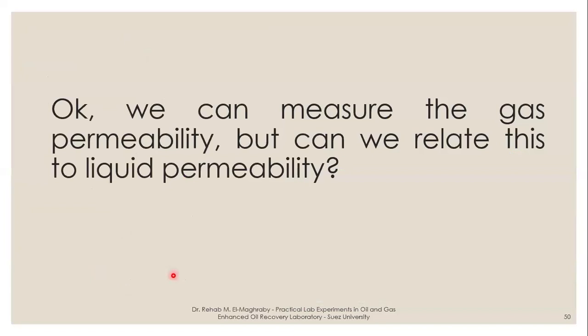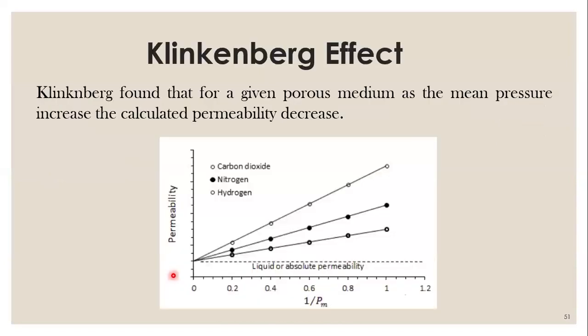Okay, but can we use this gas permeability to know the liquid permeability? Because you want to know the oil permeability, the water permeability. The gas permeability is not the one that you want to calculate. So the answer is yes. Using the Klinkenberg effect, they found that as you have different gases and increase the pressure, your permeability will decrease until you reach a certain value at zero pressure, or infinite pressure.